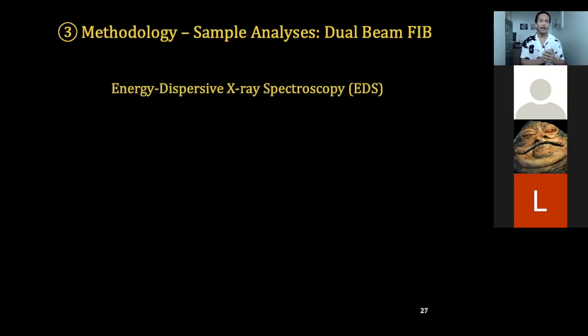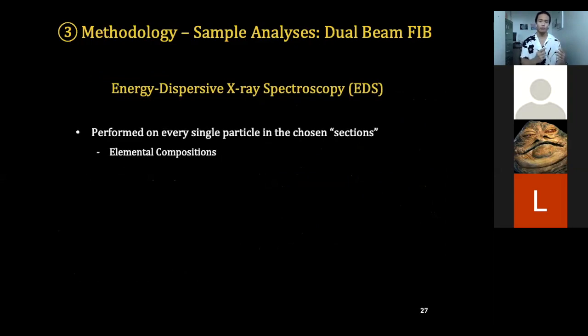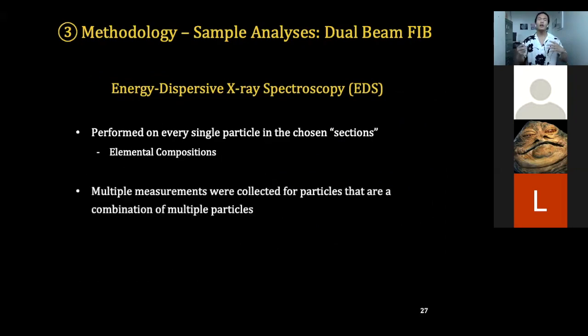After that, we perform energy dispersive X-ray spectroscopy, or EDS. And again, that is performed on every single particle in all of our chosen sections. And that gives us their elemental composition, so pretty much all the elements present in that sample and their relative abundance. For some particles that are a combination of multiple particles stuck together, we took multiple measurements so that we can get accurate measurements. And then we quantified our results with and without carbon simply because we carbon coated our sample. And so quantifying our results without carbon allows us to look at the other elements that may have been masked due to the skewed carbon numbers.